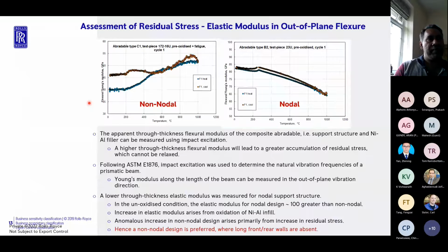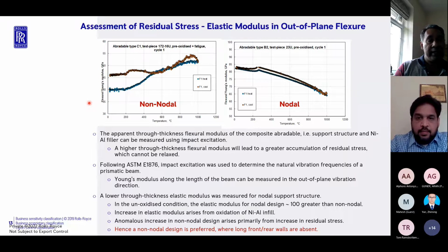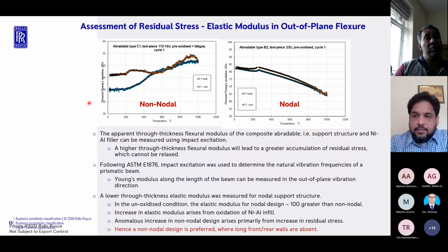Again, we used a typical ASTM type of test. We used resonance methods to determine the elastic modulus of this composite structure. So you use impact excitation, based on ASTM E1876, the basic flexural modes, or the F1, F2, F3 modes, etc., in resonance, and from that you can then calculate the effective through-thickness elastic modulus of the nodal as well as the non-nodal support structure.